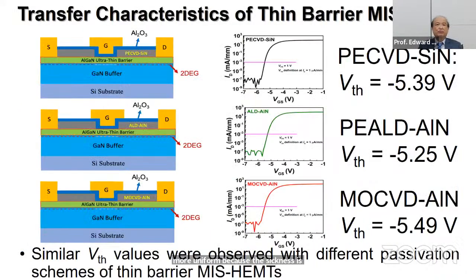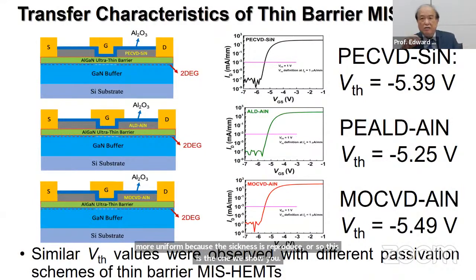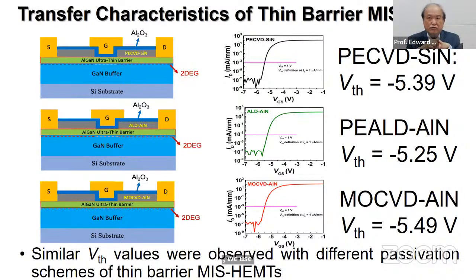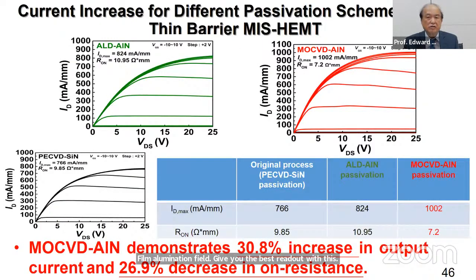So this is the one we show. We use different deposition methods to do the passivation. We have PECVD, PEALD, and MOCVD, and we have shown that the MOCVD aluminum nitride film gives you the best result with less hysteresis. So this is the comparison of these different layers. With the MOCVD aluminum nitride, they give the higher current, probably because the relief of the surface state is best, and the RON is lowest, 7.2. So MOCVD aluminum nitride demonstrates a 30% increase in output current and a 27% decrease in on-resistance.